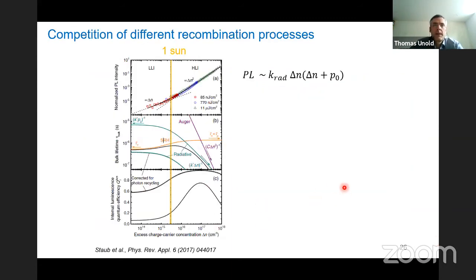And again, to show you what complicated things can go on. So it's a little busy plot. Let me walk you through. Shown here is an increase in the excess charge carrier density, which will be driven by the photoexcitation. And up here is the normalized PL intensity. You see the low injection case goes with delta N, and then the high injection case goes with delta N square. In this case, one sun conditions were just about here.